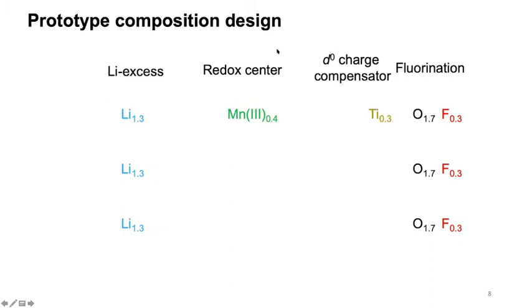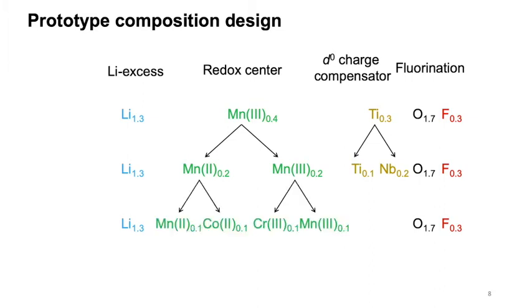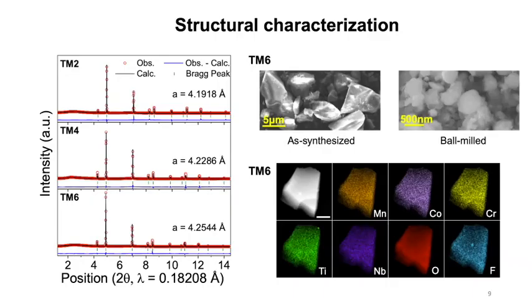And in the baseline compound, we combine manganese 3+ and titanium. And to further increase the entropy, that is to incorporate more transition metal species, now we have manganese 2+ as well as niobium so that they can reach charge balance. And we can also add another 2+ cobalt and also a 3+ chromium so that the entropy can be further increased. And these 3 materials will be noted as TM2, TM4, and TM6 based on the number of transition metals incorporated inside the structure. All 3 materials can be synthesized through the traditional solid-state method.